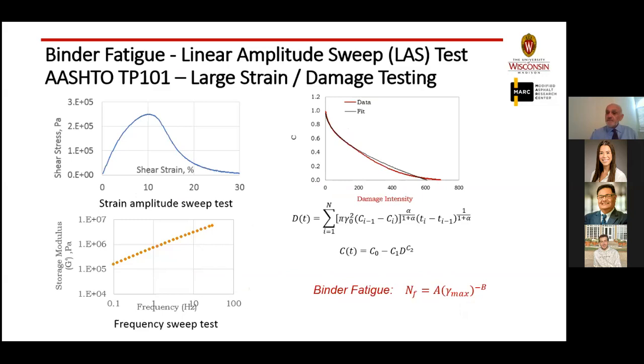So what do we do? I think several of us have worked on a new test, which is called the binder fatigue or the linear amplitude sweep. So what's the difference in the linear amplitude sweep from what we're doing? In fact, it contains two tests. One of them is exactly what we're doing today, but we run the small strain with a frequency sweep to see the time dependency of the binder. The more important part is actually the upper portion, which is called the strain amplitude sweep.